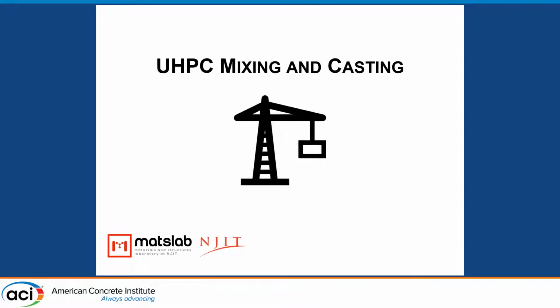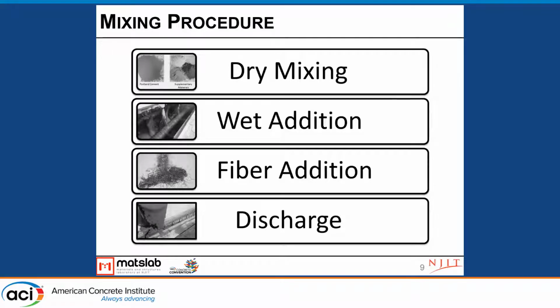Okay, so I want to talk about some of my experiences while mixing the UHPC and casting the UHPC in the molds for G109. A typical mixing procedure for UHPC in a shear mixer is first dry mixing. We add all the solid materials and powders and mix them. The next step is wet addition, which is the addition of water and admixtures. After we get a paste, we add the fibers and make sure they mix enough to disperse and give a homogeneous mix. At the end of the mixing procedure, we discharge these materials.